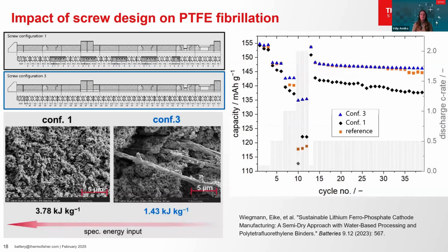The screw design determines the specific energy input applied to the material. Here you see two screw designs with 5 mixing blocks and one without any mixing blocks. Below are SEM images of LFP cathode material mixed with PTFE using the two screw designs.